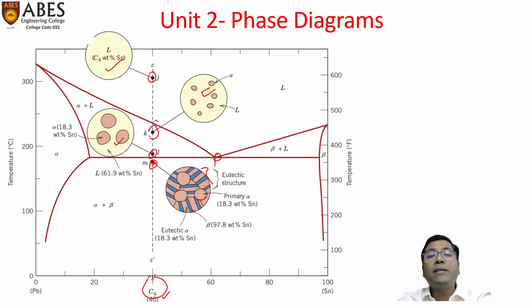Primary alpha would also be there. These are the primary alpha. The chunks generated here will remain, and as we cool further, these chunks will remain. Also this liquid, which was available here, at this point will transform into this lamella, or alternate layer of eutectic structure, alpha and beta. So at any point in this region, at this temperature, three things would be there: primary alpha, and also eutectic alpha and beta.